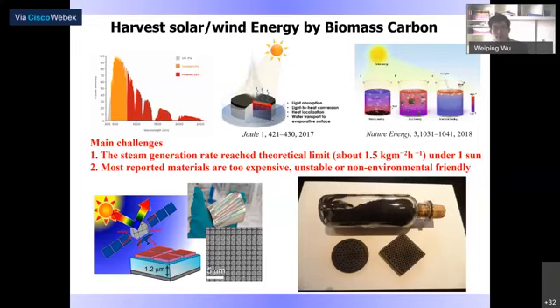Towards this end, there are two major challenges. The first challenge is that the steam generation rate nowadays has reached very close to the theoretical limit. It's about 1.5 kilogram per meter squared per hour at one sun. And the most reported materials used are either gold nanoparticles or carbon nanotubes or other materials. They are quite expensive or unstable, or they're not environmentally friendly.